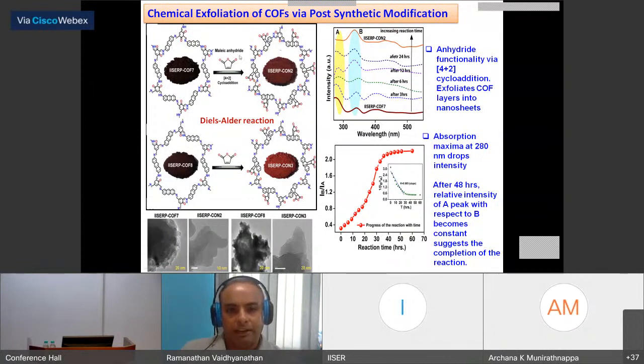The maleic anhydride. So after the COF is formed, in a post-synthetic fashion, I do this 4+2 addition on the anthracene site, and depending on stoichiometrically how much maleic anhydride you use, I can control how much of this adduct formation I can create. And this is very nicely monitored using UV-visible spectroscopy. So this peak at 270 nanometer is a signature of anthracene units. And as I keep adding the maleic anhydride and keep the reaction going, you can see this peak is losing intensity. Whereas the other peaks, due to other functionalities in the COF, do not lose any intensity.